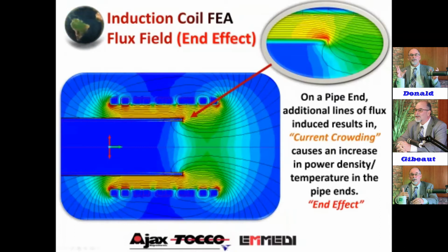Now, if you look up in the upper right corner, that shows how the fluxes are actually migrating. Each line of flux has a certain amount of current in it, and the more lines of flux you have, the more current you're inducing. So if you're wrapping around the edge with more current, you're going to overheat it because you're inducing more current in the same mass rate. And the corner ends up overheating, as you see here in the upper right. But you can slow this condition down. As you go lower in frequency, the lines of flux go further apart, so you can slow this condition down with frequency. But mainly in the material handling, it has to be precise enough that the best way to do it is get the right frequency for the application and keep the pipes butted all the way through.